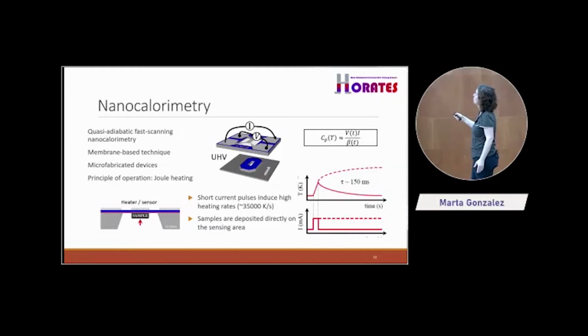For instance, how does a nanocalorimeter look? Let me show you. Here. This is a nanocalorimeter, okay? This is a microchip. I don't think I have the dimensions here, but this is more or less half a centimeter by 3 millimeters, something like that, 5 by 3 millimeters, okay? And what do we have? We have a membrane, you see it here. This is a silicon nitride membrane. And on top of that membrane, we deposit a platinum circuit, okay?